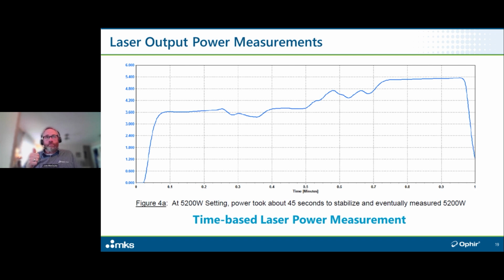Well, you can't really do that with a pulse to power system because you're firing it for just a second or a split second, and you're getting one single number back, right? So although the pulse to power is a good indicator, it's good for tracking laser consistency over long periods of time. If you do have a problem with your laser, it's really not very good for troubleshooting what your laser is doing in that time.